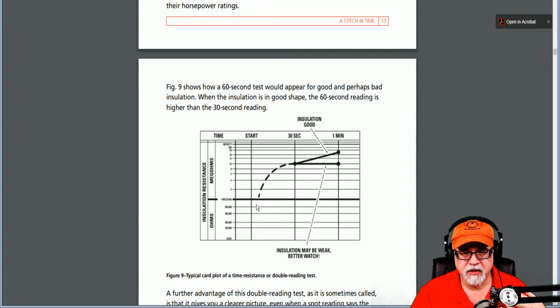So as you can see here in a picture, those that are watching, you have another test that I'm telling you is the 60-second and 30-second. So watch the value at 30 and then take the value at 1 minute. Now, this is better than the spot test, which is just a 60-second, 1 minute test, because you don't get the real picture of the rise, okay? And you get past what we call that capacitive point, and it starts to go up. So spot testing at 60 without any other observation is not my recommendation.